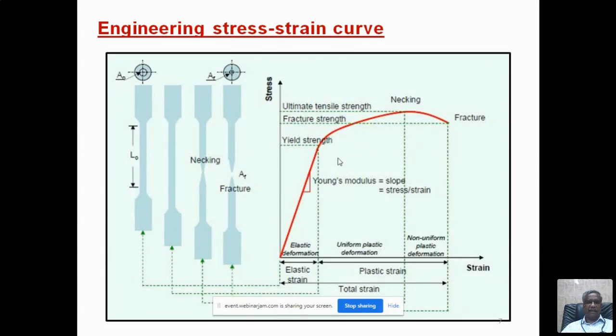And once it is fixed, you apply the load, and from the first stage to the second stage, you see that there is an elongation, an extension of length. You can see that the second specimen, when compared to the first specimen, is slightly longer. This is noted by the arrow mark in that position on the stress strain curve. If you keep on increasing the load at the loading rate, then at one stage the specimen will neck. Necking means there is a sudden reduction in the cross-sectional area or the diameter. The necking is at the maximum load the specimen can take; at the maximum load condition, the necking will start.